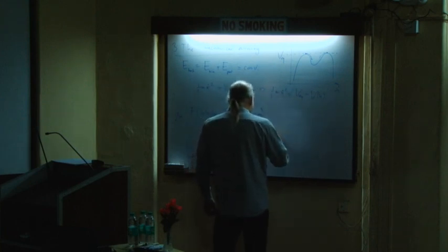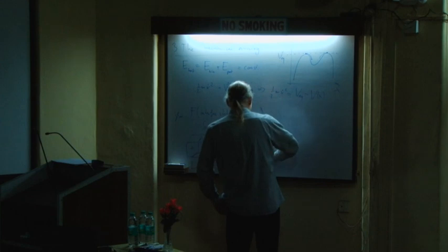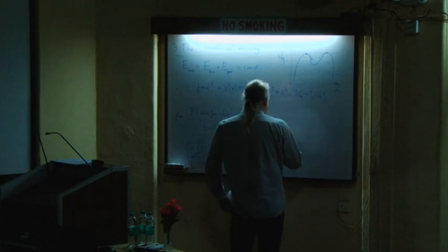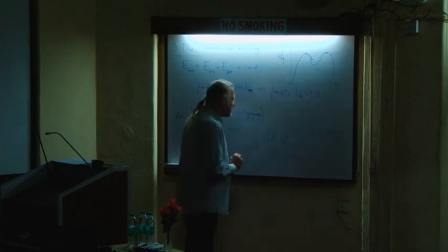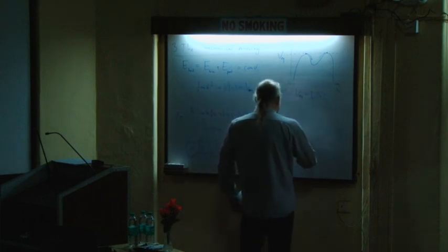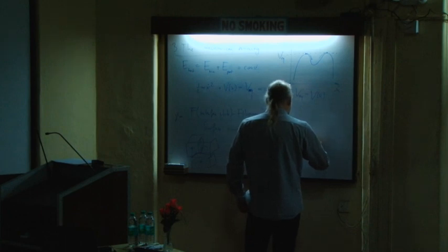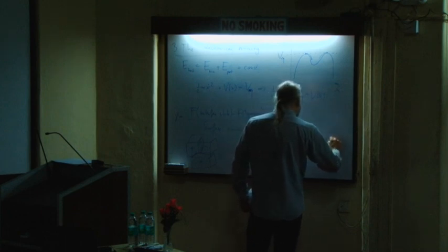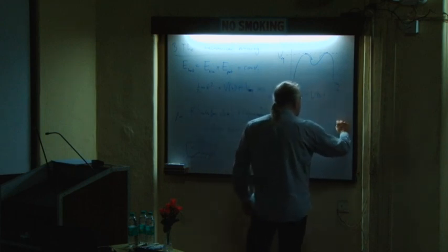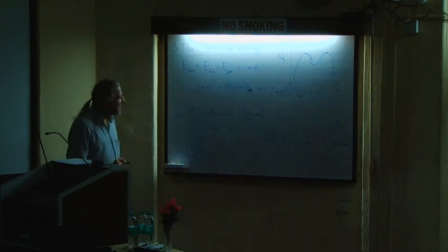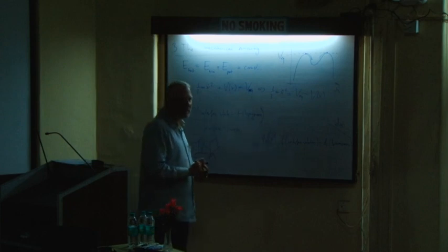So I can write gamma is equal to the integral of my free energy density with the interface solution minus the free energy of the homogeneous state, and this, no, I do not have enough space, but here you have just a dx. So the surface tension is given by a one-dimensional integral.